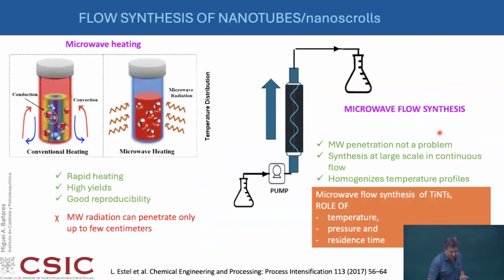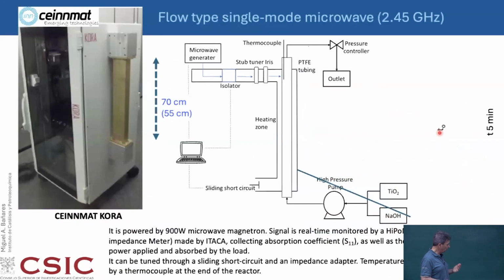Now, you can do the same thing with microwaves. They do that in a batch reactor, but we say, okay, why don't we do that in a flow reactor? Because then you can have additional control systems. The first one is that when you make it by batch, people are working on making titanium nanotubes, ceria nanoshapes like nanocubes, nanorods, nano-octahedra. You can control that, but the productivity is very little. So if you make it in a continuous flow system, you can continuously be producing something. That's why we decided to use this microwave flow system to do that.